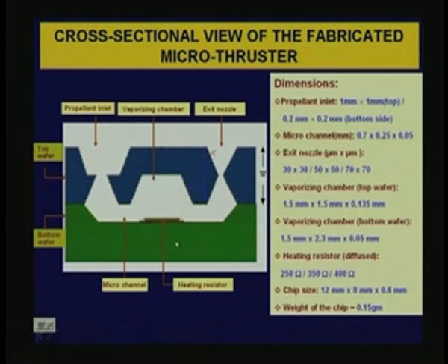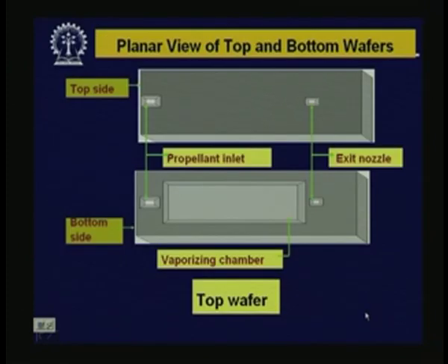The heating resistor is a diffused resistance; we have made different structures with 250 ohm, 350 and 400 ohm. The total chip size is 12 millimeter by 8 millimeter by 0.6 millimeter thickness. The weight of the total chip is 0.15 gram, a very low weight. So that is what we have fabricated in our laboratory, and you can see the cross sectional view of the top and bottom wafers.